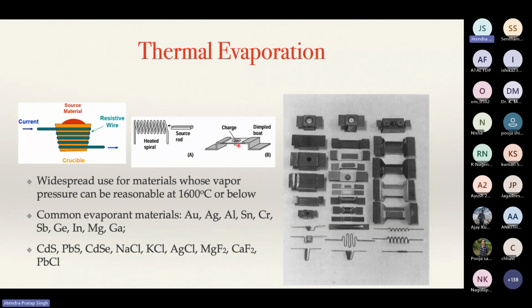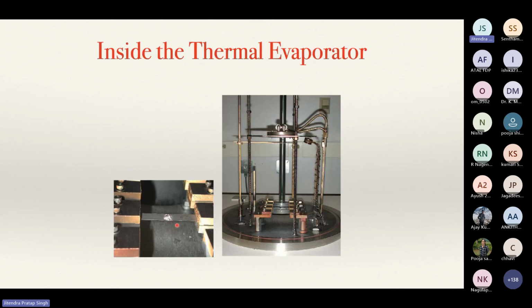Now, if we go inside the thermal evaporator, I'm just showing you. These two points are the electrodes. The electrodes are tightened here, and these are copper electrodes. You pass the current, and we pass very high current here. The current can be of the order of a few hundred to 400 amperes. It depends on what material you are depositing.